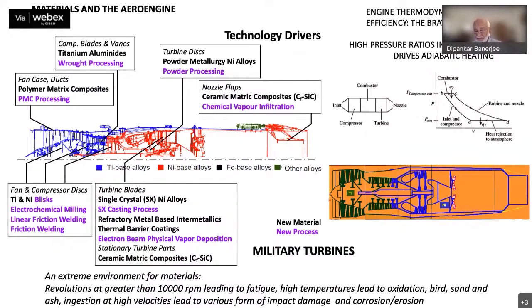One is titanium, which is used in the front parts of the engine, the fan and the compressor, to about 550 degrees centigrade. Nickel-based alloys are used in the hottest parts of the engine beyond the combustor, that is in the turbine, where temperatures can rise as high as 1600 degrees centigrade. And then there is the gradual increasing use of ceramic matrix composites right now in the rear of the engine as convergent, divergent flaps and so on.